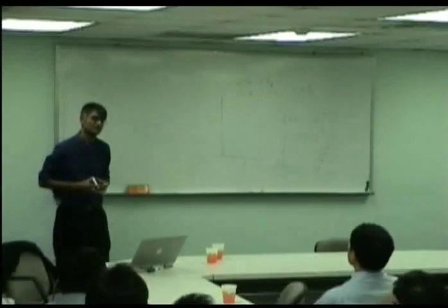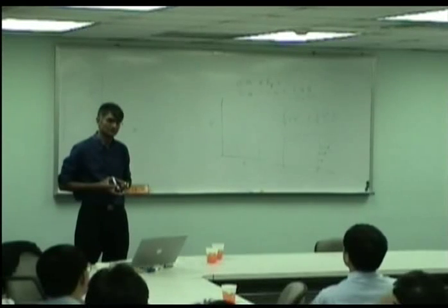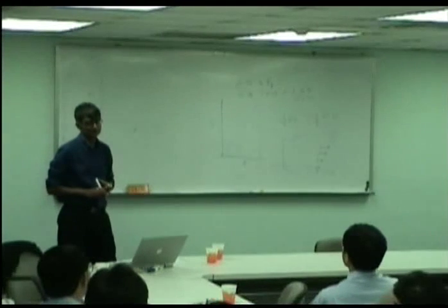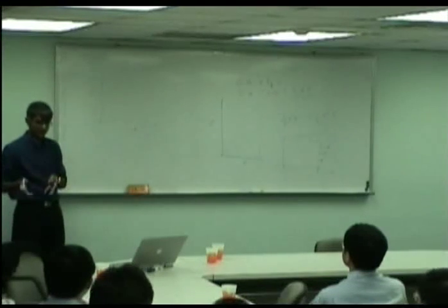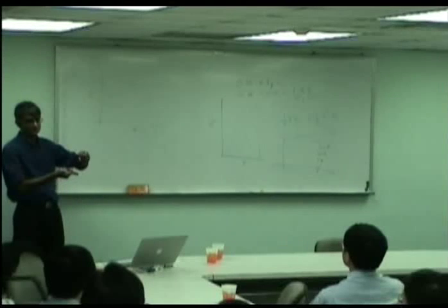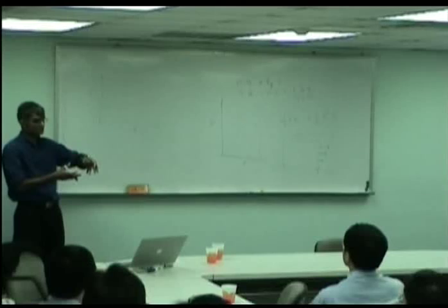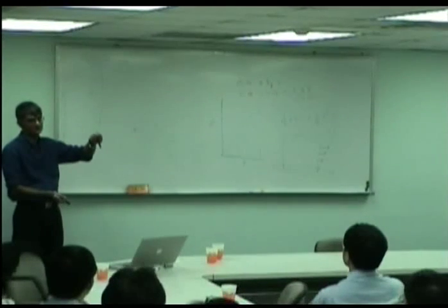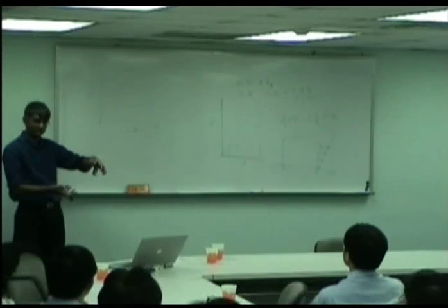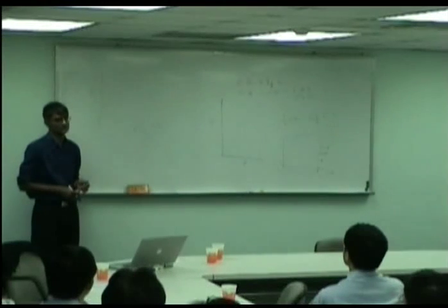So how about the location of martensite during plastic deformation? Location of hard phase. Right. Because you see any contribution. You know, if you get the balance between the hard and the soft phase wrong, that means you've got a large fraction of hard phase, then you will get void formation. Because the martensite won't deform until the ferrite has hardened. And if the ferrite is accommodating all the deformation, that's okay if the fraction of martensite is small, but it's not okay if it's large.